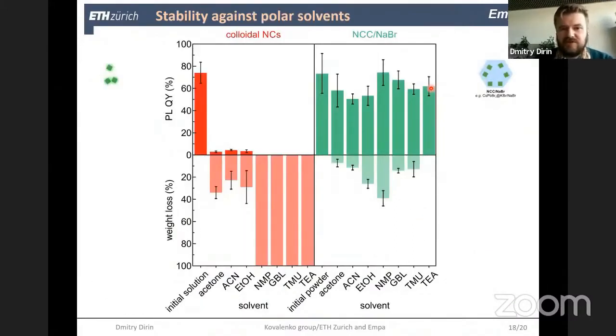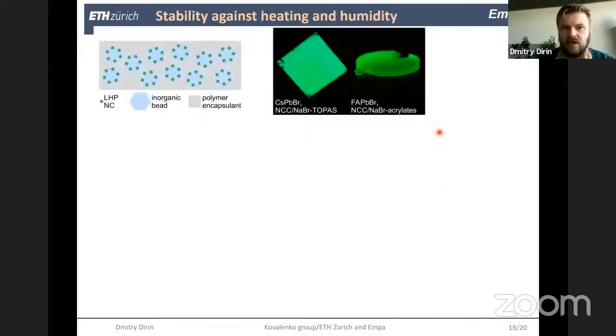And the most important part is here in the last two slides. We can see that this material indeed exhibits much better stability against polar solvents. I can give you a comparison with colloidal particles, which completely die if we try to wash them with acetonitrile or ethanol or such polar solvents like gamma-butyrolactone, for example. In contrast, our material can be ultrasonicated in those solvents. But this is only part of it.